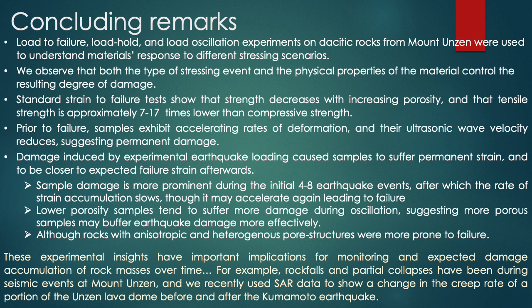Damage induced by experimental earthquake loading caused samples to suffer permanent strain and to be closer to expected failure strain after the oscillations. Under compressive stress, we see that porous samples may buffer load oscillations more effectively, although their lower absolute strength implies that a similar scale of event may render them more likely to fail.